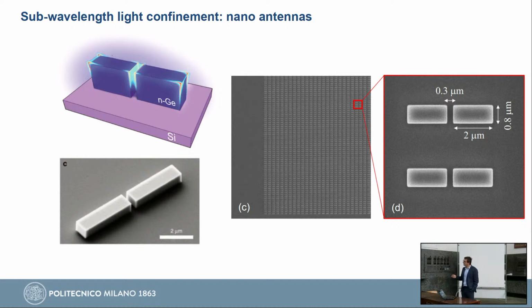And so again, I want to stress that this kind of almost perfect fabrication, you can have it only in semiconductors. There are no other simple tools to do it with a metal or whatever material. You can make it on a large area with a very high reproducibility. So this is a zoom on these arrays of nano antennas from the top. So you see that the gap is only 300 nanometers.